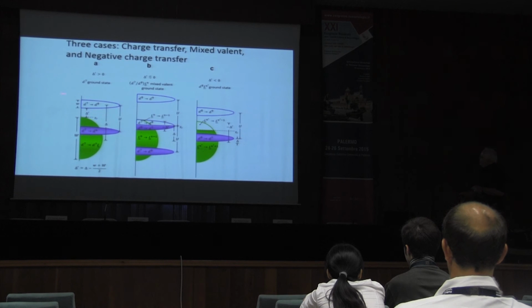So let's say that we assumed that we had a positive charge transfer gap, a large charge transfer gap, but not as large, larger than the U, smaller than U, okay? So that we could have the charge transfer excitation, the band gap would be determined by this delta prime. I would have the upper Hubbard band, I would have nickel, I would start with D7, so these excitations would be electron addition, to d8, and these would be electron removal, to d6, so you would have a U, right?